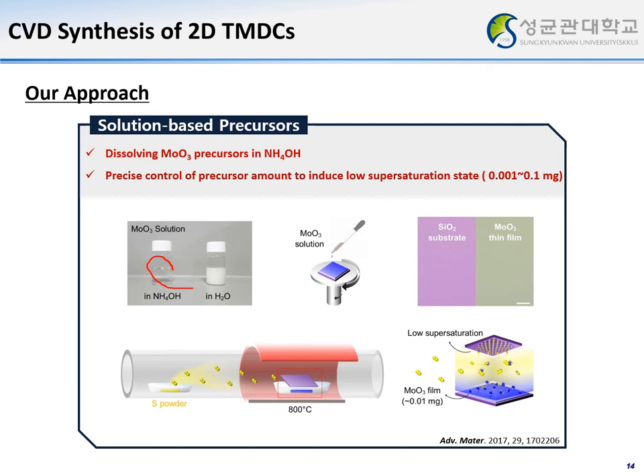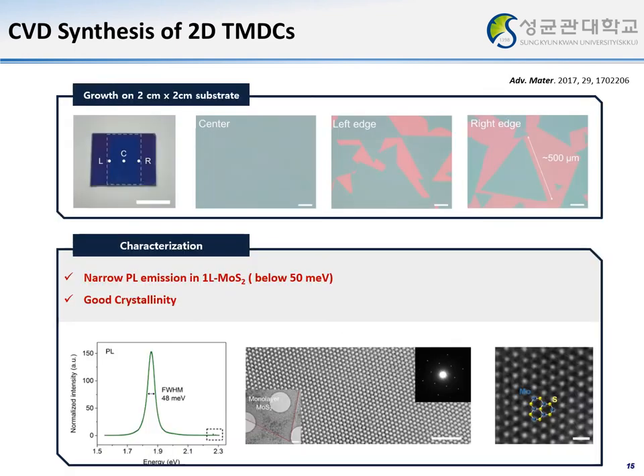For our synthesis, in order to increase the diffusivity of the precursors and maximize the precursor utilization, growth temperature was raised to 800 degrees Celsius, which is a little bit higher than previous reports. This can be done because we are using very small amounts of the precursors. Extremely small amounts of precursors result in inducing very low supersaturation level near the substrate, which then leads to lower nucleation density on the surface of SiO2.